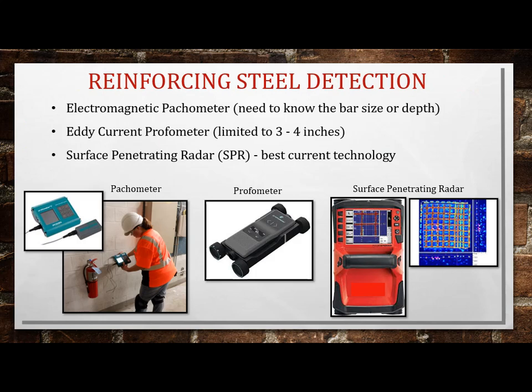So the current tools used to detect reinforcing steel, I mentioned three of them here. One on the left is an electromagnetic pachometer. It's based on magnetics. It's a sophisticated metal detector with a very narrow focus. Pretty good for detecting rebar and tendons to a depth of about 5 inches. They're getting harder to find. They kind of stopped making those. Now they've moved towards these eddy current devices, profometers. They only go about 3 or 4 inches, but it's kind of the new technology that came out.